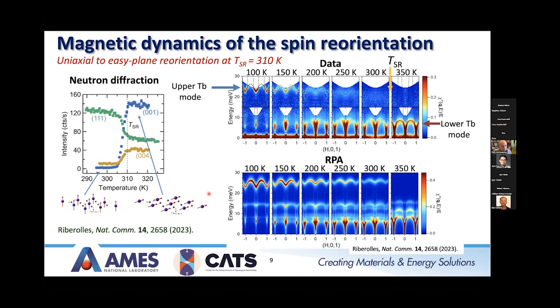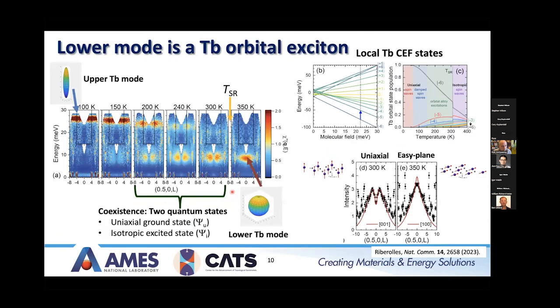Rob was able to recreate this behavior doing some RPA calculations, and the development of the RPA was in conjunction with Chris Stock's group and Stephen Wilson's group. He was able to recreate the spectra pretty well, including the spin reorientation transition. One thing that is noticeable is that the RPA does predict a lot more modes that are not seen in the data. So this upper terbium mode, we now know, is associated with the uniaxial terbium anisotropy.